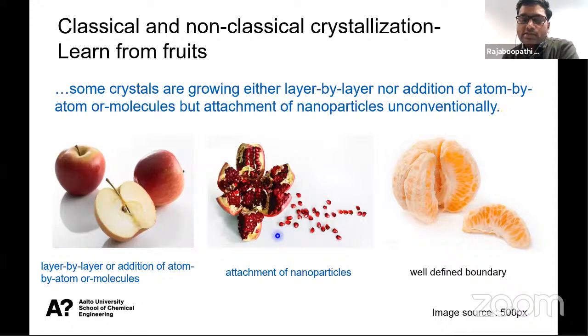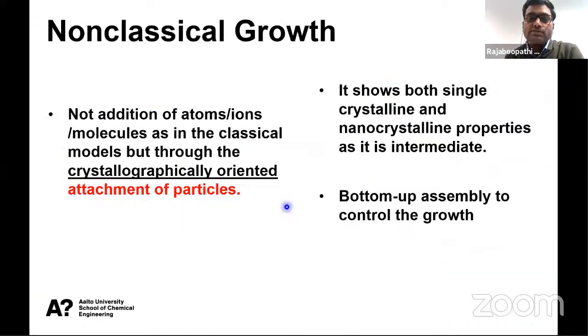In the case of non-classical growth, whether it is a hierarchical material, mesocrystals or oriented attachment, there are different things. If something happens due to particle attachment, we can say it is non-classical growth, like the pomegranate. If the particles have a particular orientation, a well-defined domain, for example if you grow some magnetic material, it has some well-defined orientation and well-defined boundaries. So we can say these are non-classical growth. If anything happens due to particle attachment, we can say it is non-classical. If anything happens by atom addition, we can say it is classical. So the hierarchical structure comes under non-classical growth of crystals.